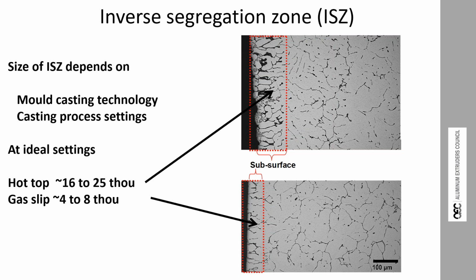Richard, it's Danny. I just want to jump in here. This inverse segregation zone here, and the size of this inverse segregation zone, is very, very critical in high tensile strength alloys, not just because of the amount of bark, I will call it, that's on this, but we typically use less clearance between the OD of a block and the ID of a liner in the higher tensile strength, or even softer alloys again, because they have a smaller area in which they can be extruded.